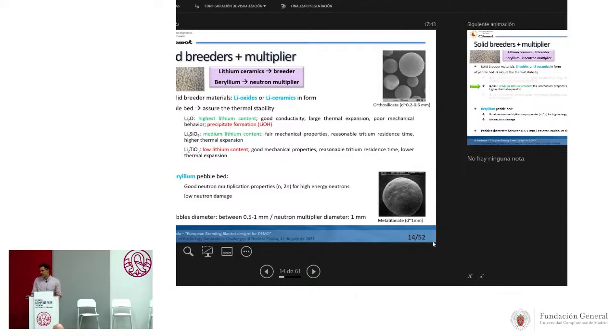The first one is the lithium oxide, which is really interesting because it has the highest lithium content, but it has a quite important disadvantage, and that is that it precipitates the formation of lithium hydroxide, and this means that at the end we are going to lose lithium and tritium, and we can't recover tritium easily. So for that reason, we go directly to lithium ceramics. In the case of the lithium ceramics, we have studied two main ceramics, the lithium orthosilicate and the lithium metatitanate.